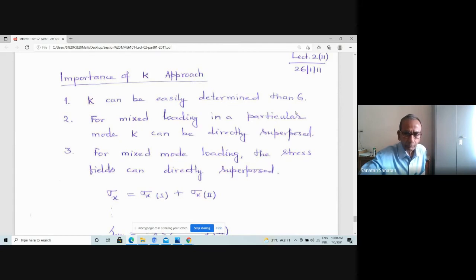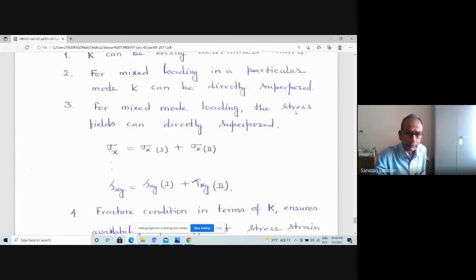And for mixed mode loading, the stress fields are also something which can be taken up. So if you have a problem involving more than one mode, then the stresses are obtained by just simply superposing the stresses in the individual modes. Like sigma x in a mixed mode problem is nothing but sigma x in mode 1, that's subscript 1, plus sigma x in mode 2, and if a third mode is also there, you can superpose that, and therefore you can calculate the stresses in the mixed mode also very easily, routinely.